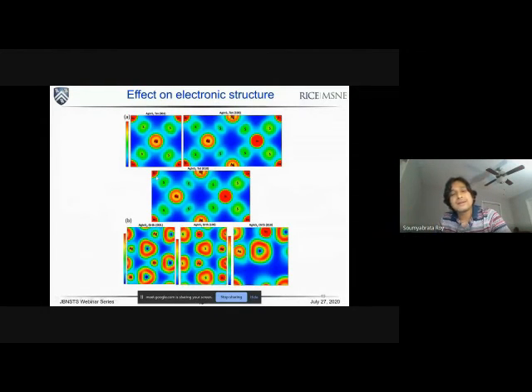And because the neighboring coordination environment in these two systems is different, they have different charge distribution among indium and selenium. And what happens is, basically, when you have this charge separation, as I told you, CO2 specifically binds on these surfaces, right? And if you have a particular charge distribution or charge separation, that can break the chemical carbon and oxygen bond to a certain extent, depending on how the charge separation is.